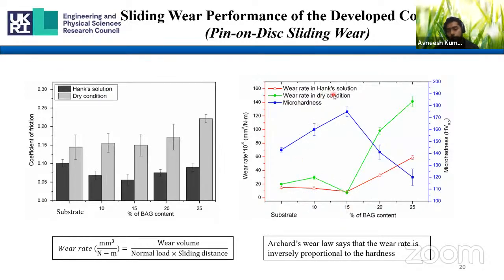Then in simulated body fluid condition, only two coatings were able to protect the substrate, that is titanium with 10% baghdadite and 15% baghdadite. And the reason can be explained with the hardness. The higher the hardness, the better the wear resistance.